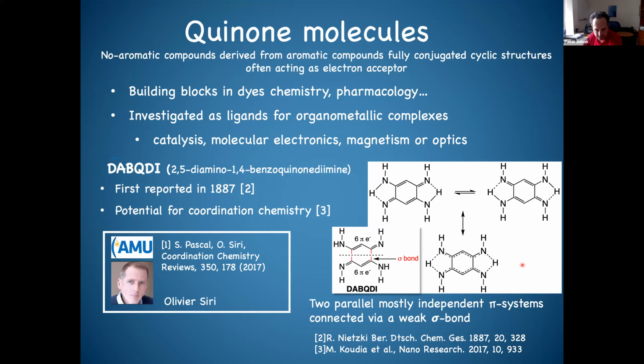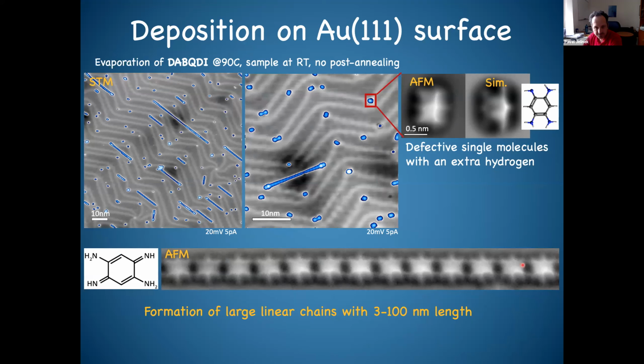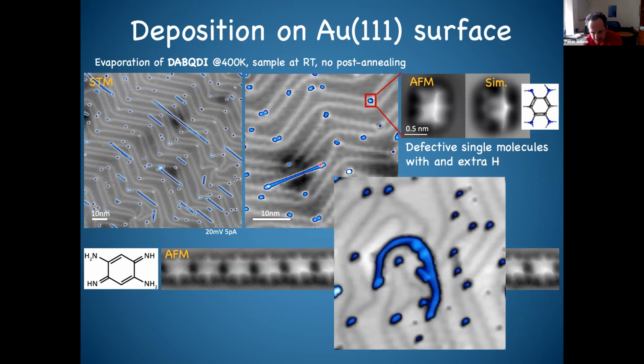So we start with this and put it on a gold surface, and what you see here is that we have some residual molecules, which we found out later by high resolution imaging are extra hydrogenated molecules, because the stuff is a little bit tricky. But the important thing is that if we do this deposition at low temperature, we get very nice straight chains, which also feature some edge states, which you see here. This is an experiment at 5K.